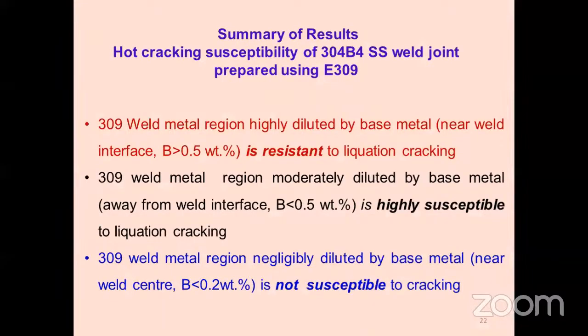So now we can see why this 309 weld metal is more prone to cracking because of base metal dilution. The weld metal which is undiluted by the base metal is not susceptible to cracking. The region highly diluted by the base metal, where the boron content is higher than 0.5 weight percentage, is resistant to cracking. And the region where it is falling between 0.5 to 0.2 weight percentage of boron is highly susceptible to cracking.